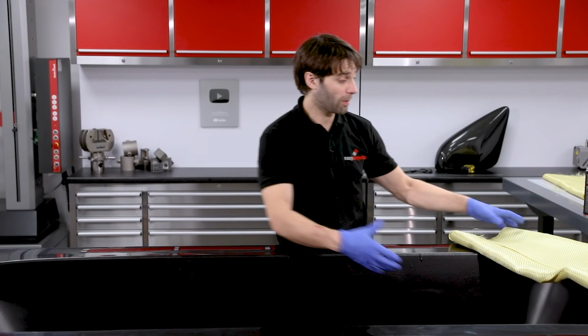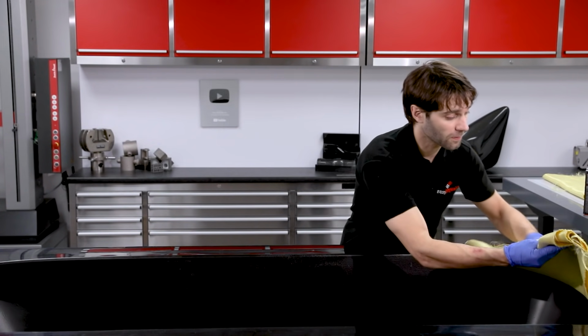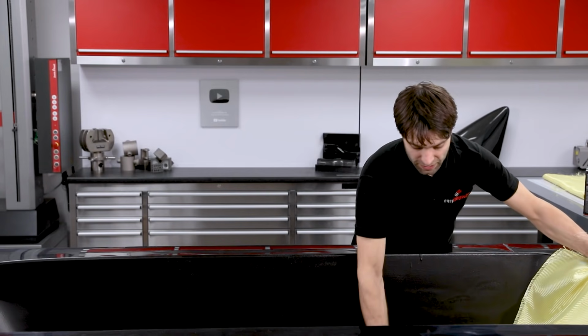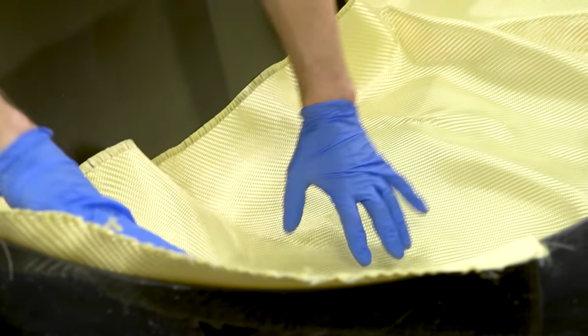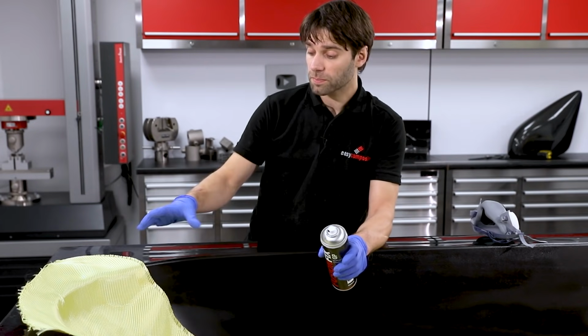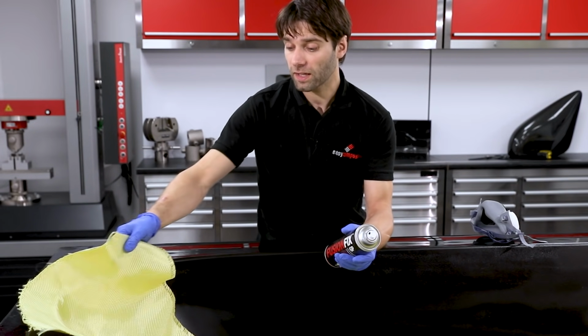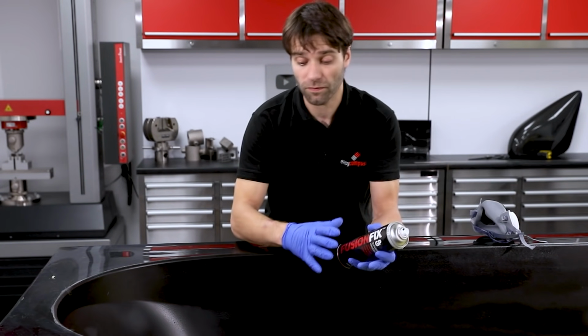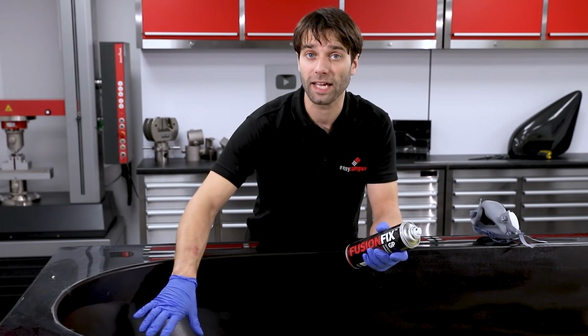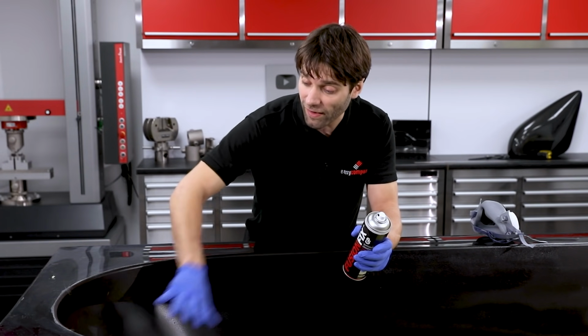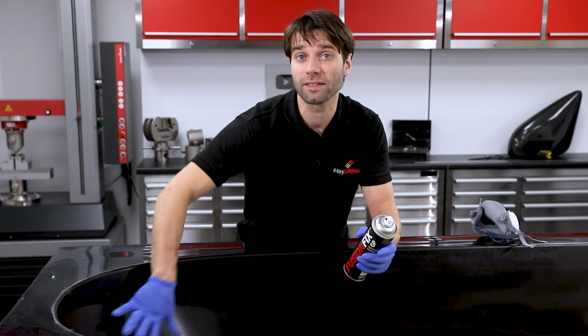I'm going to begin the layout by positioning the first layer of reinforcement. So that's simply a case of rolling it out over the surface of the mould and getting an approximate position. With the first ply loosely positioned, I can now peel this back and then use the Fusion Fix spray adhesive to secure it tightly in place. Now I'm able to do that directly onto the surface of the mould because we've got a pigmented gel coat.